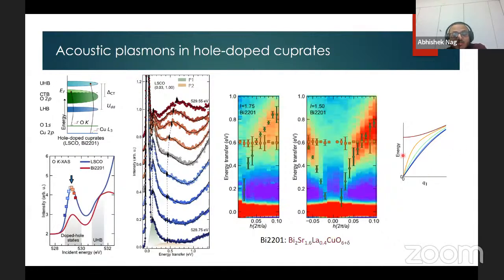We did the same scan for another family of cuprates, the bismuth-based single-layer cuprate, which is commonly termed as BISCO. And again, we find similar sharp dispersing features in the momentum space. Now, since all the excitations in these layered cuprate systems are two-dimensional, whether or not these are really acoustic plasmons can only be confirmed from their interlayer character.